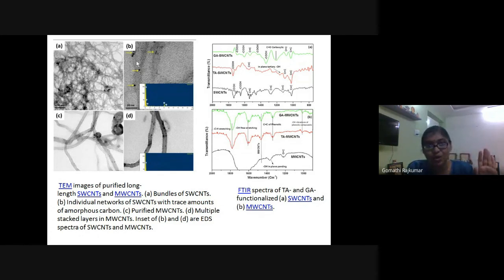So this was single walled, and here you could see some purified multi-walled carbon nanotubes where you could see 1, 2, 3, 4 layers here. But whereas here you could see all just single strand of hair. So this is one multiple stack layer where you could see 1, 2, 3, 4, 5, 6, and 7 layers of multi-walled carbon nanotube being produced. So this picture shows the kind of carbon nanotubes that we produced, both single walled and multi-walled.